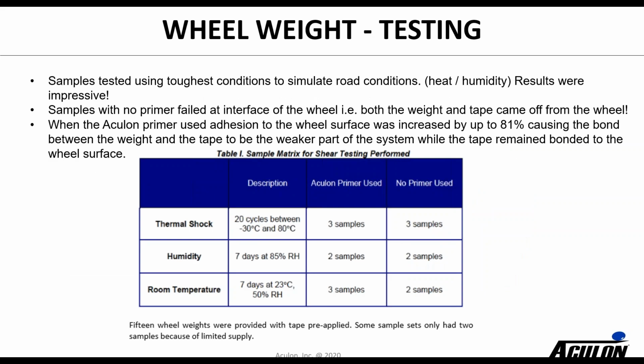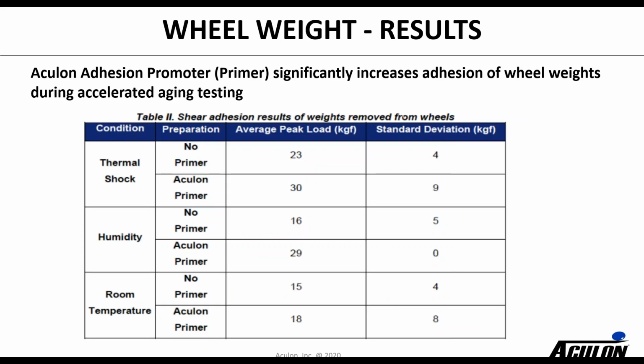So I think we have some data to show on that, but the key thing in a lot of these adhesion issues is looking at when the part or the system is being stressed. A lot of times it's relative humidity, heat, and water that can really interfere with good adhesion. Improving that bonding is important. So here are some of the results. You can see, especially when you compare no primer versus our primer in a humid environment, a big increase in adhesion. And so ultimately, whether it's thermal shock or humidity, you're really seeing the improvement by using the Aculon treatment.